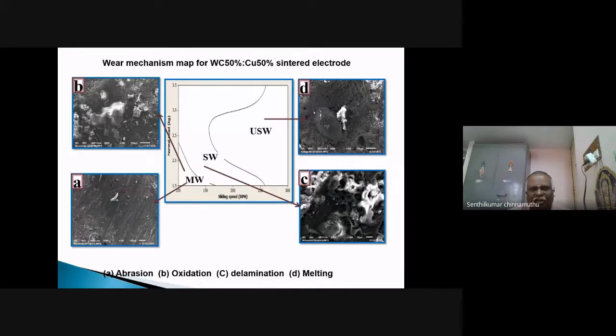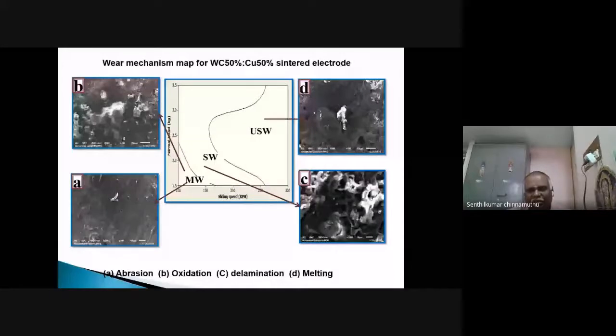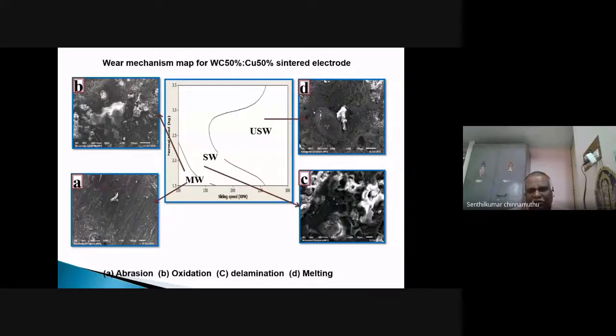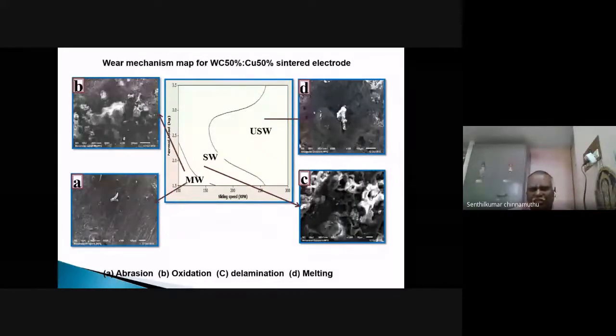So if the design engineer wants to design a component of 50% copper, 50% tungsten carbide sintered electrode, the safest sliding speed is 100 to 160, and the normal load is 1.5 to 2.4. In the severe wear region, if you increase the sliding speed beyond 160, delamination takes place. In the earlier case, you might have seen that up to 200 is the safest, but in this case delamination occurs at 160, because in the semi-sintered electrode more material is deposited, whereas in the sintered case the layer is very thin. So the delamination takes place earlier, and ultra severe wear takes place at about 250 RPM